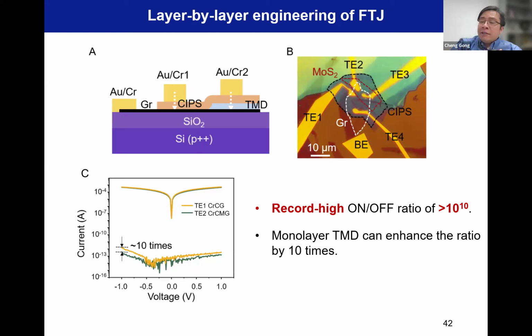The second one is, as I said, FTJ fundamentally depends on two asymmetric, two non-identical electrodes. But in traditional FTJ, you just use two different 3D metals. Here, we use 3D metal chromium and 2D metal graphene. So such electrode asymmetry is very prominent. So this is the second reason, electrode asymmetry. The first one is a clean band gap, so no indirect tunneling.